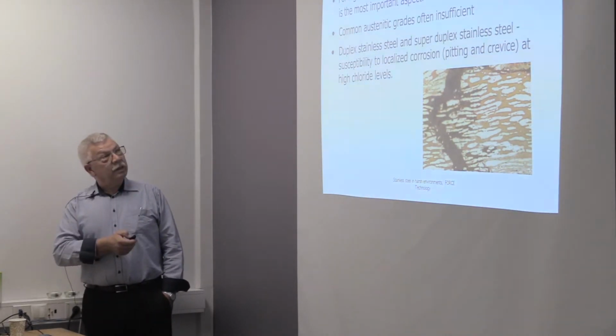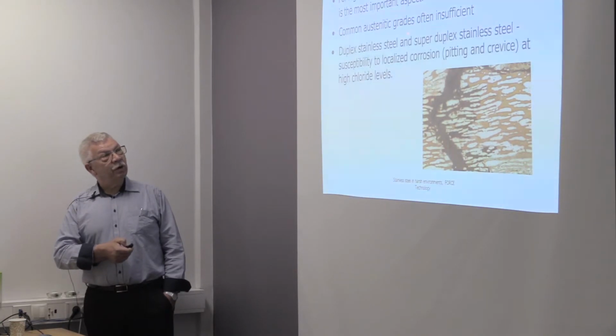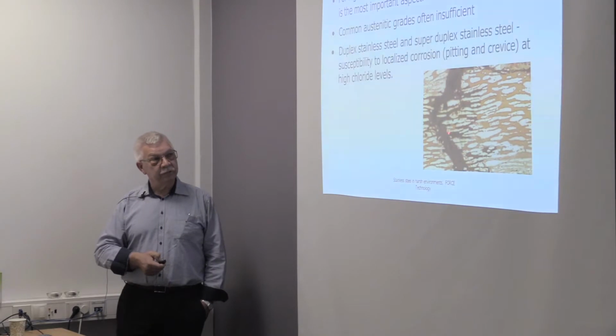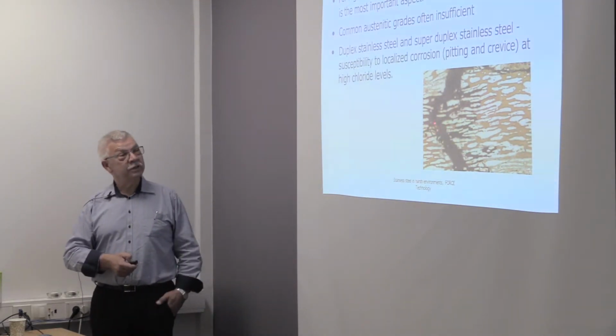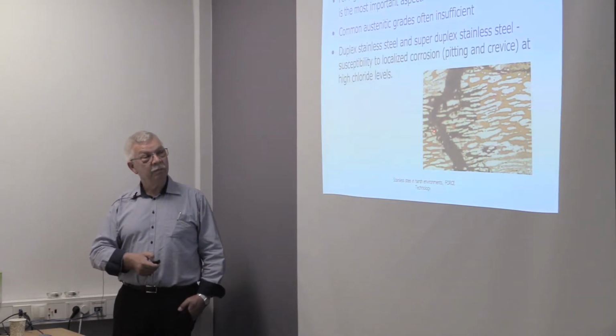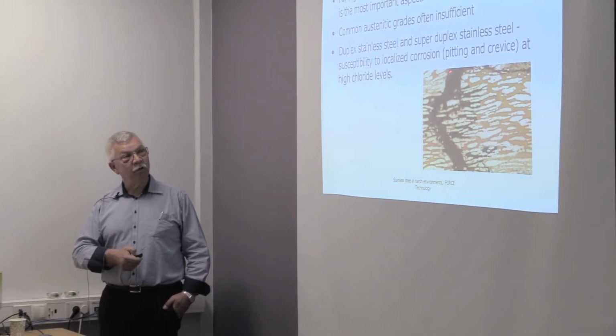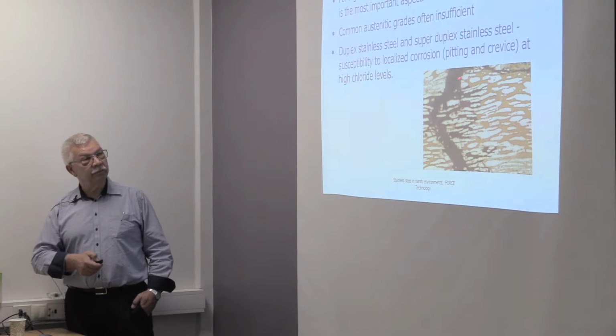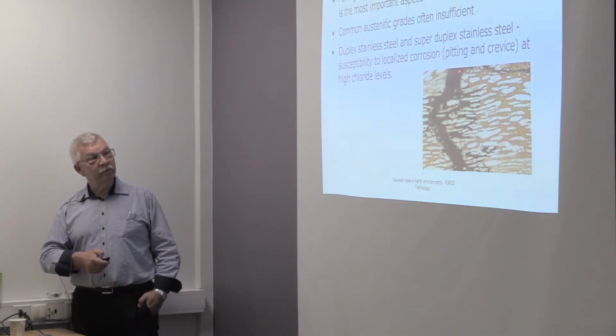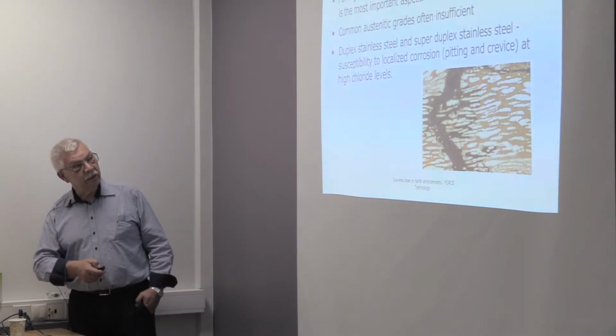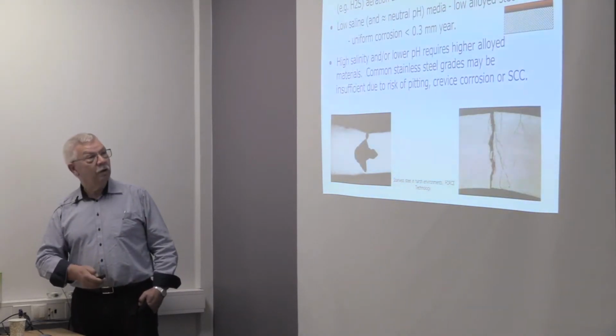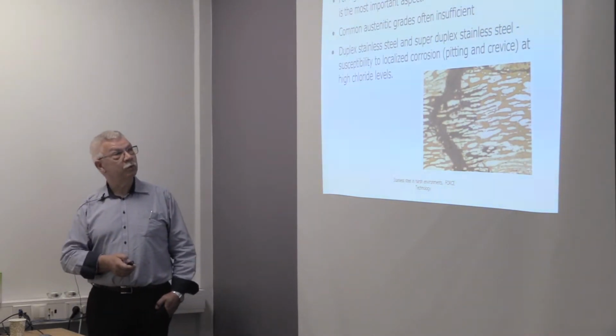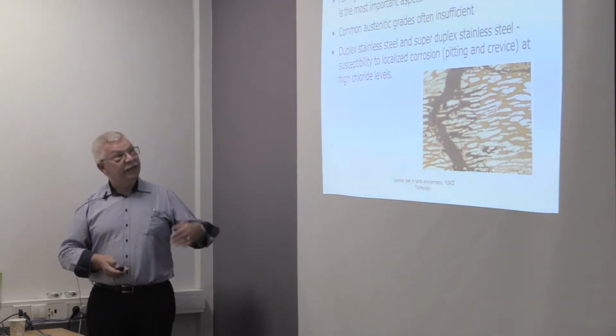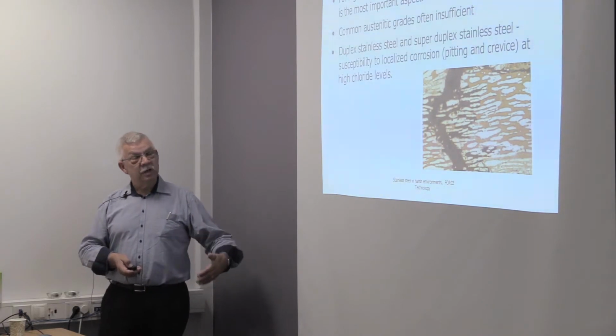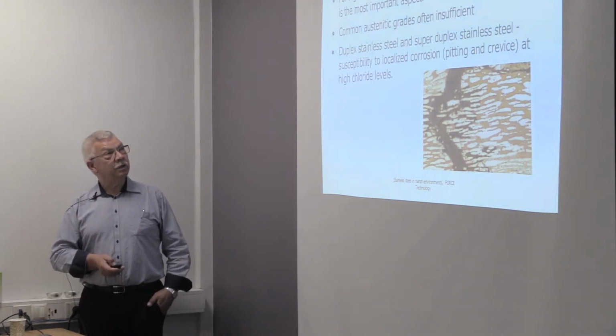So even the duplex stainless steel might not be enough. This is from an autoclave that is high temperature, which also could be present in geothermal brines, with a high chloride level. And in fact, there was a crevice below a plate in the autoclave which would concentrate the chlorides to a level where we have stress corrosion cracking and selective corrosion. In this attack, it's the ferrite part of the stainless steel which dissolves in the corrosion process. So there will be a limit for temperature, salt, and chlorides for this more common stainless steel.